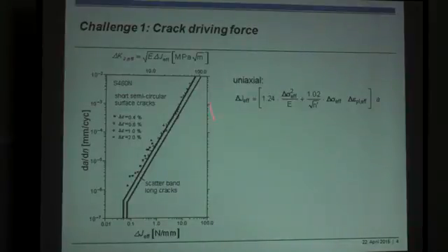What we do in fatigue is that we cannot calculate this J integral by making a path around the crack tip or something like that. That is totally out of range, so we very much rely on some approximation suggestions originally brought forward by Dowling, and also adopted one of his formulas.